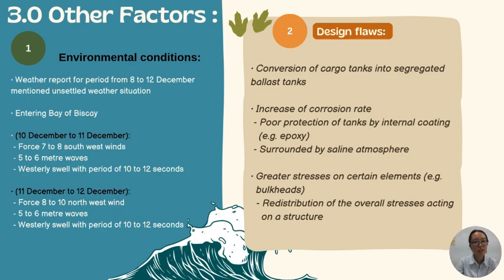The second factor is the design flaws. The conversion of cargo tanks into segregated ballast tanks for the Erika increased the corrosion rate, as these tanks are poorly or even no longer protected by the internal coating, and the surrounding seawater creates a saline atmosphere. It may also lead to certain elements having to withstand greater stress due to the redistribution of the overall stress.